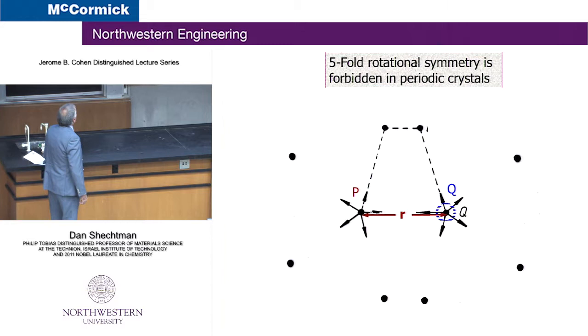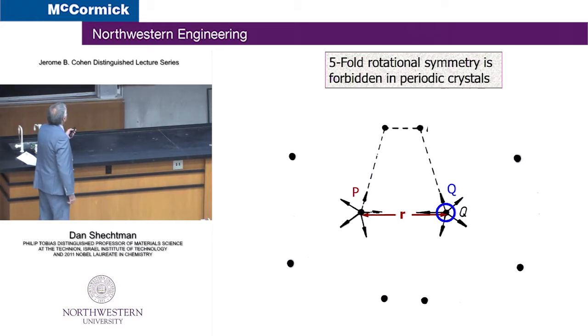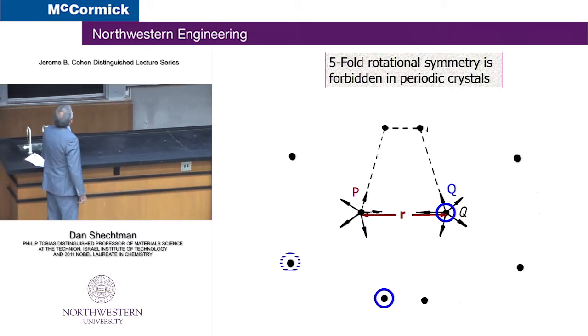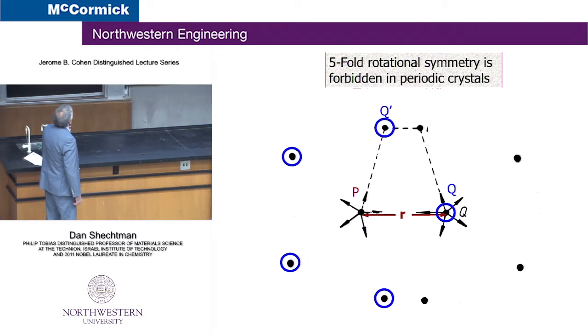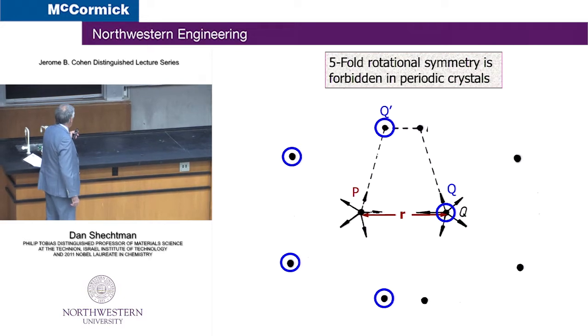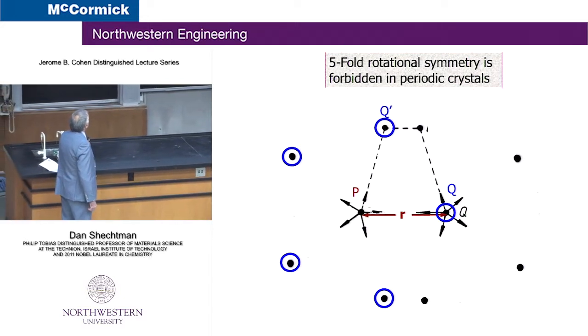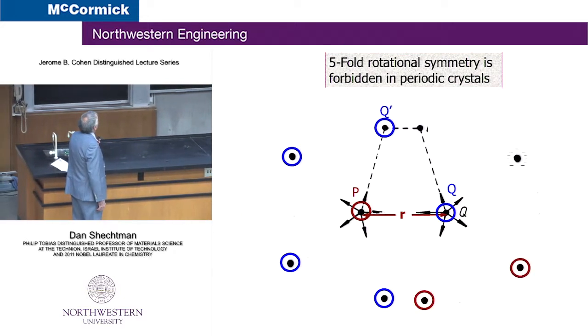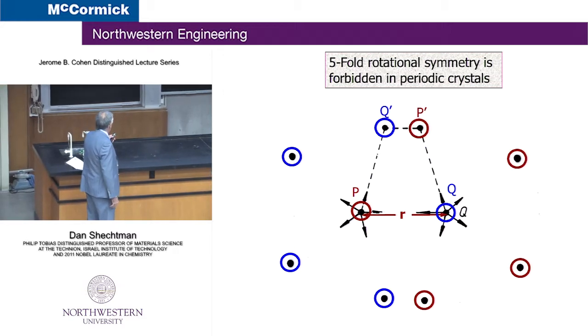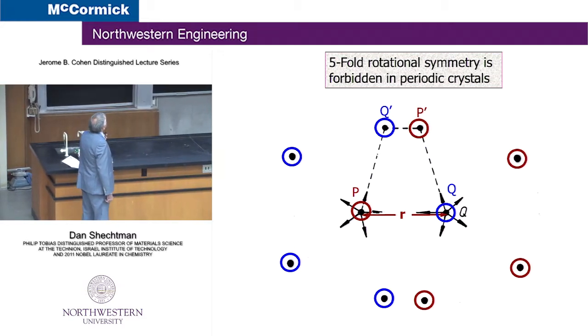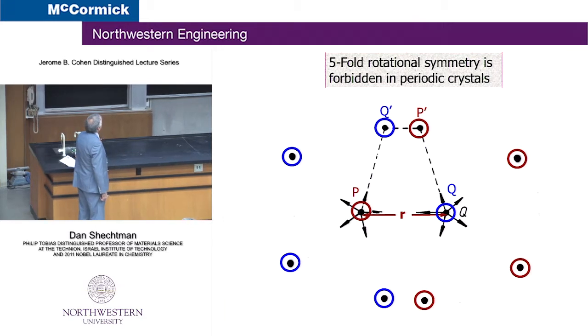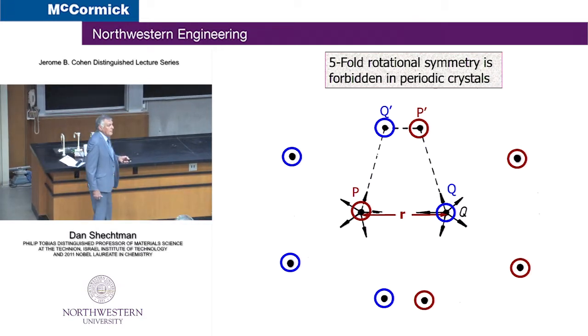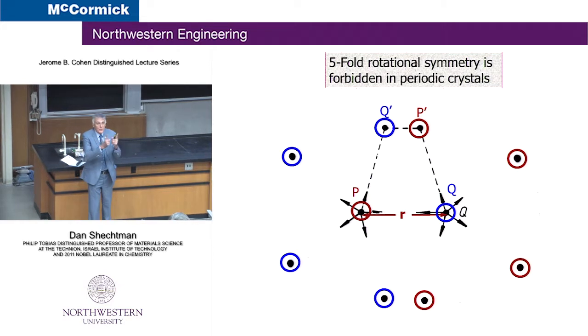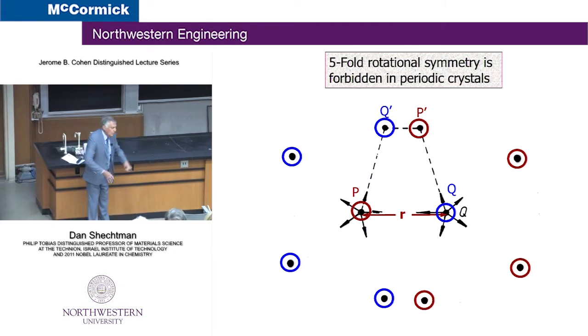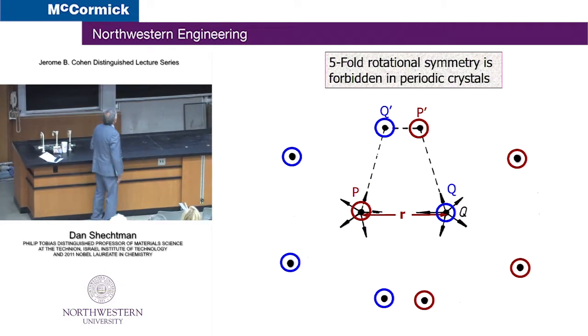Okay, so here is Q right there. 1, 2, 3, 4, and 5, and we should have a Q prime atom here. This is if the 5-fold rotation symmetry is allowed. Now, what about P? Here's P, 2, 3, 4, 5, and we should have a P prime atom there. But the distance Q prime, P prime is shorter than r, as you can clearly see, and this is impossible because we chose the 2 closest atoms. Okay, no 5-fold rotation symmetry in crystal.